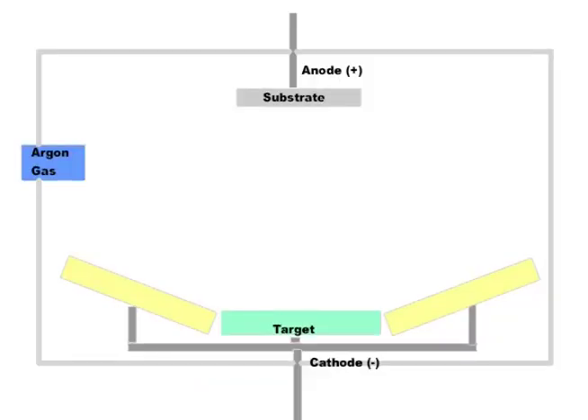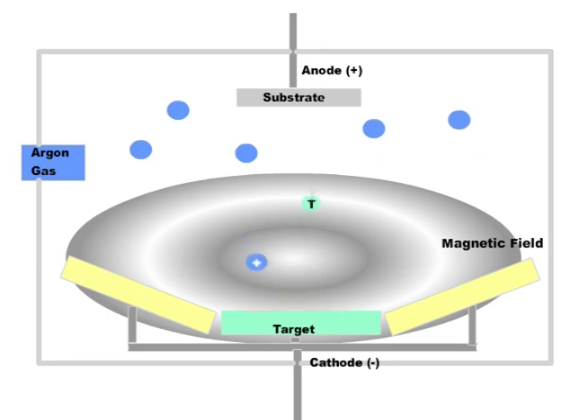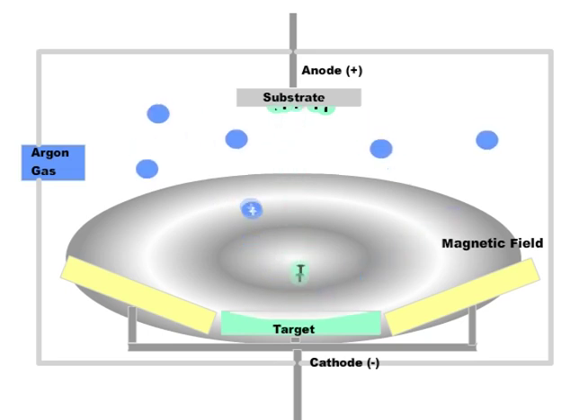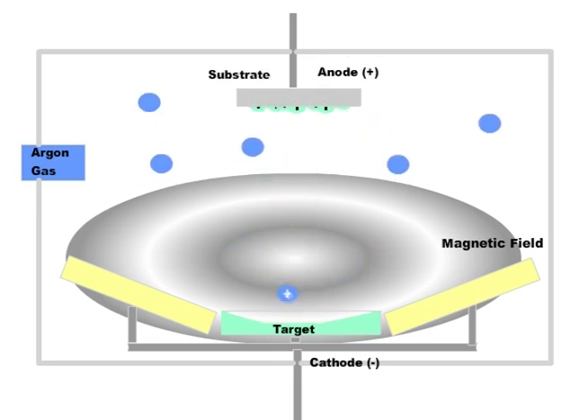This is how magnetron sputtering, or any sputtering device, typically works. Argon gas comes into the system, and below you have your targets, and that is labeled as a cathode. And on top here, where the substrate is being mounted, is your anode. So at the target, it's going to be a negative power, and the argon gas coming in positive ions. The attraction could be mild, or the attraction could be hard, depending on how much power and how much pressure this particular deposition is going to take place. And then once this attraction happens, this material is being etched off or removed from the target, and that causes a plasma. And that plasma is being deposited onto the substrate, which is located directly above the target.